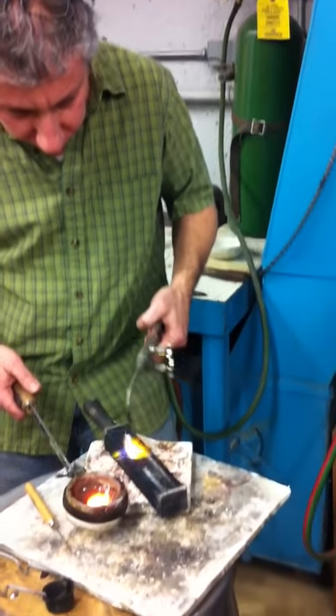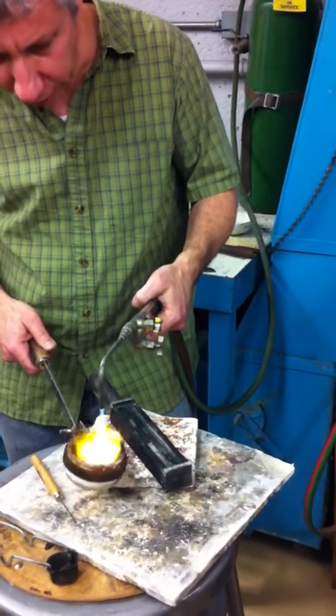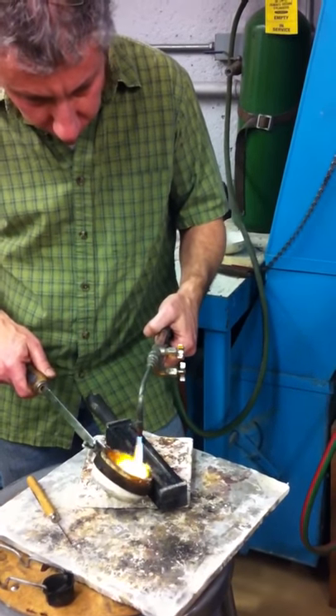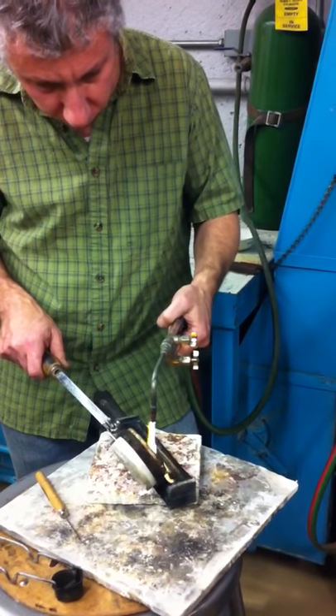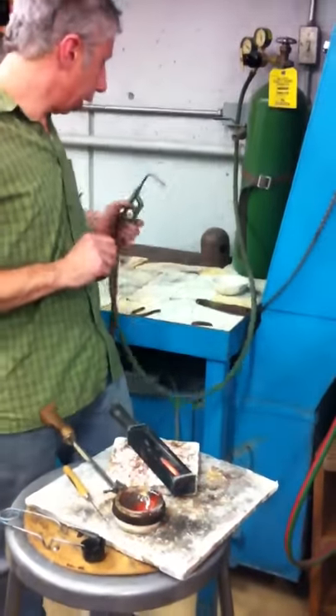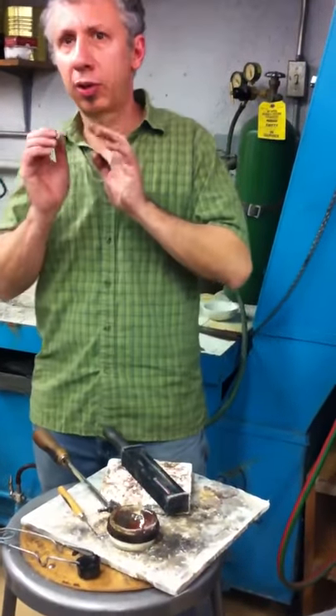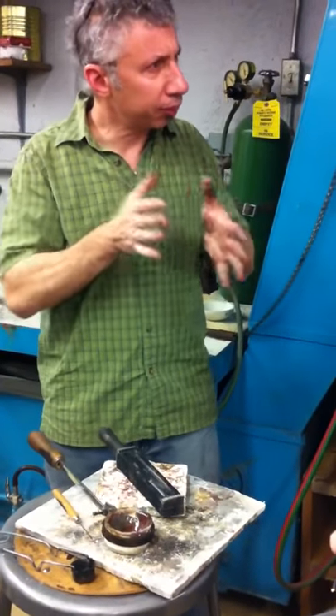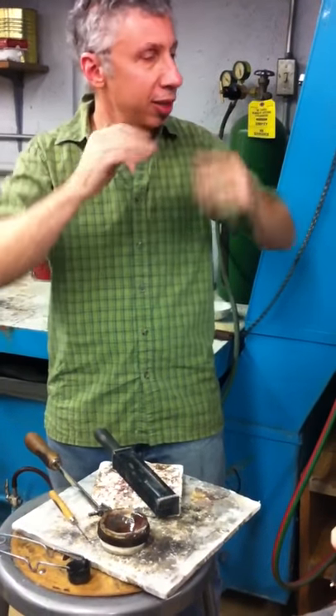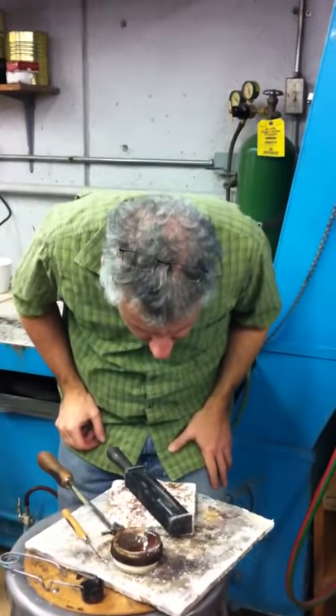Take a break from it for a minute. Isn't that beautiful? Make sure that there's none of that crap in there. Now I can tell if it's a good ingot — good meaning that it's going to do what I want it to do. The way it looks: what I'm looking for is, as it cools off, it gets this charcoal, like a chocolate or eggplant kind of color. And as it cools, fissures develop in the surface — not deep ones, but just cracks in the oxide. It's kind of this silvery color, then a coppery silvery color. Then I kind of know it's worked. It's starting to happen.